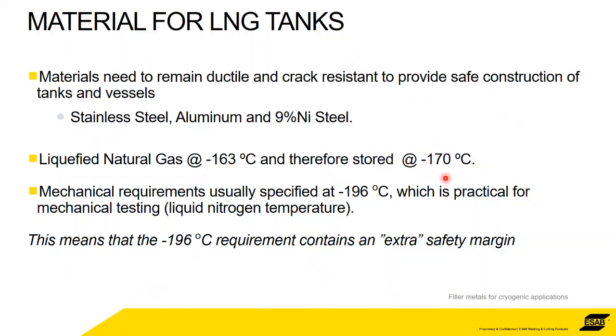However, when specifying the base materials and the filler metals, we specify them with properties at minus 196. The reason being that that's a very typical, common temperature at which test laboratories can operate, because it's the temperature of liquid nitrogen. So we're using liquid nitrogen to basically test for LNG fabrication. So if we know that the properties of the filler metals and the base metals are all right at minus 196, then to handle minus 170 should be no problem at all, and that's what they do.